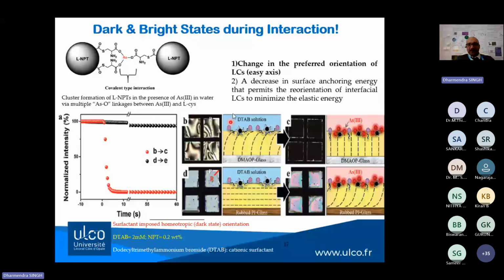The first mechanism is the change in the preferred orientation of the LC, that is called the easy axis, and second, a decrease in surface anchoring energy that permits the reorientation of interfacial LC to minimize the elastic energy. So here the surfactant, as I told you, imposes homeotropic orientation, and when the moiety is present, then it will change into the planar alignment.